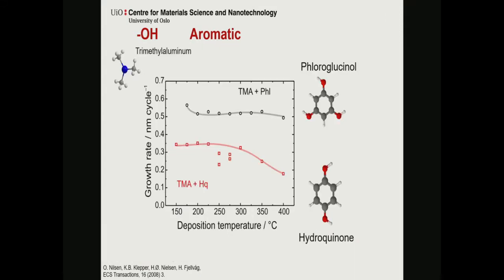This alcohol base also reacts subsequently. This is the thickness as deposited when you then run to your reflectometer. Perhaps you haven't run fast enough, because over time the phloroglucinol version increases in thickness, whereas the hydroquinone decreases in thickness over time. So there's not a complete version there. But what you notice as well, they are fairly stable with deposition temperature, and you can deposit a stable material up to kind of nice high temperatures without the anions decomposing.